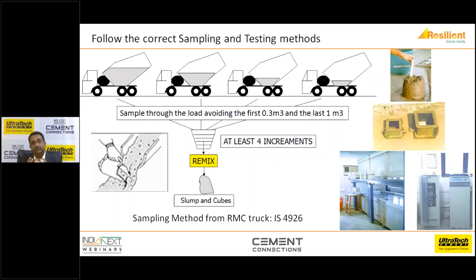You should let go the first 0.3 cubic meters of the concrete which comes out of the truck mixer when you do the sampling. And you should not take the sample from the last 1 cubic meter of the truck mixer. So you have to take in 4 increments whatever is between the first 0.3 and the last 1 cubic meter of concrete, remix it properly, and then cast the cubes with that.